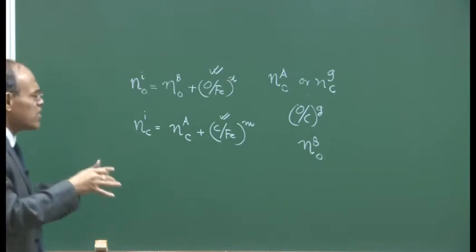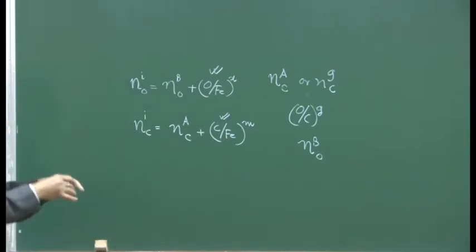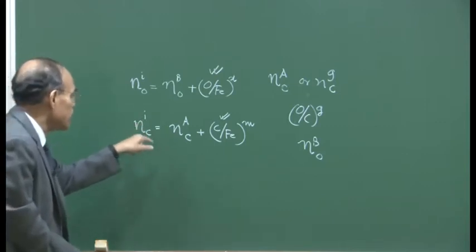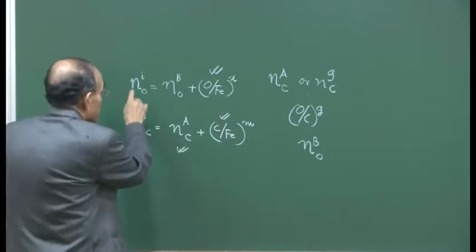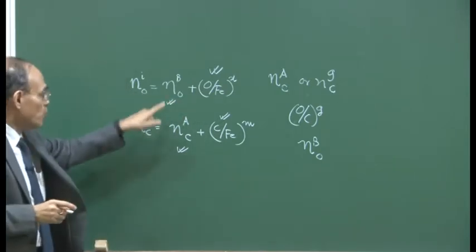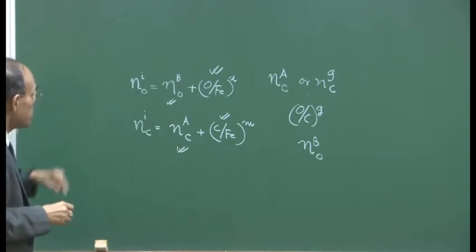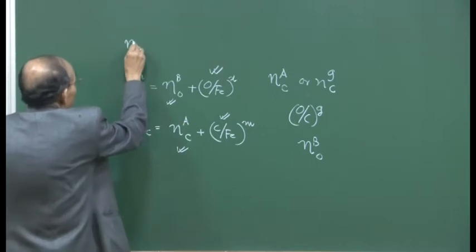So all these variations of iron bearing materials can be accommodated through an O by Fe, which can be calculated depending on the composition of the DRI being charged, or in what proportion we mix various iron bearing materials. The input of carbon can be calculated once the active carbon is calculated. Similarly, the input of oxygen can be calculated. So the two parameters will explicitly give us the input of iron and input of carbon. What about the output?